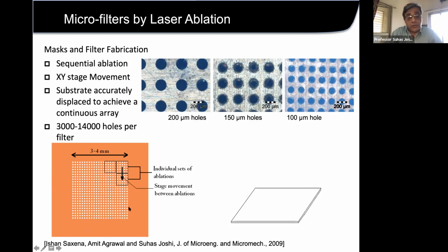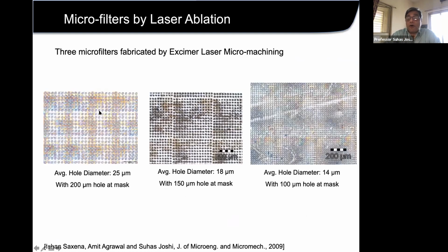And so now I can go to one position, move the table, and perforate the whole surface. Though again it was a very tedious process, we could make the mask with 200 micrometer holes, 150 micrometers, and 100 micrometers, and then we could actually make the polymeric surfaces. What we call the filters, the microfilters, with some kind of spacing, 25 micrometers, 18 micrometers, and 14 micrometers. So very, very small.